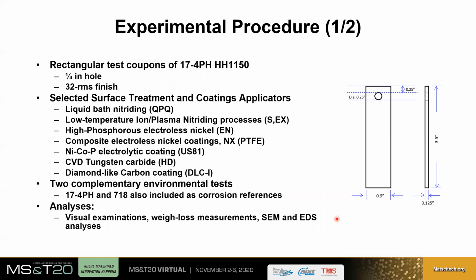So with this, here is the experimental procedure. First of all, we had to acquire a test article made of 17-4 PH. We acquired, I believe, 5 or 6 dozens of those. The samples are shown here on the right. So these are essentially rectangular coupons. And once acquired, they were dispatched to a number of professional surface treatment and coating applicators, mostly based in the US, but also in Europe.